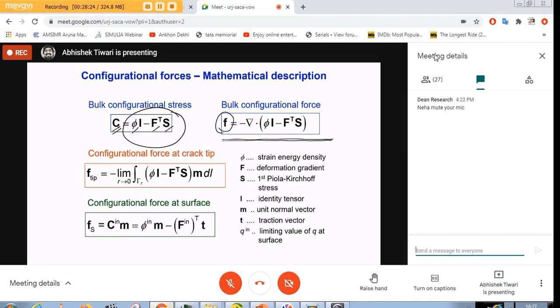Advantage here is that we have not assumed anything about the material or the loading type. So we are not saying that the material has to be elastic, non-linear elastic. The material can be deforming in any way, and there can be unloading, there can be creep deformation, and therefore this concept is valid under any type of deformation: creep, viscoelasticity, elastic, plastic, or completely elastic. So this is how we calculate configurational forces in finite element analysis.